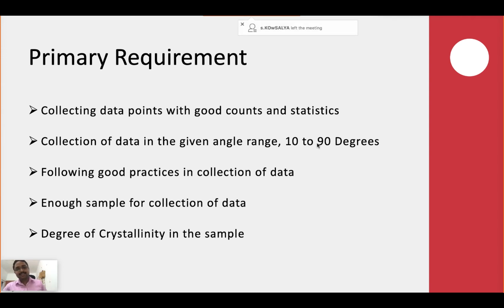Less than 10 and greater than 90, there will be a lot of effects coming into the picture due to the instrument. Those will contribute to your particular diffractogram. So the standard thing will be 10 to 90. If you are not getting any peaks greater than 60 or 70, you can stop at 70 itself. What I usually do is take from 10 to 70. If it is not satisfactory, I can go for 10 to 90. So better you limit to 10 to 70. That will be enough, and that also is very good data. According to samples it will vary, but as standard you can take from 10 to 70.